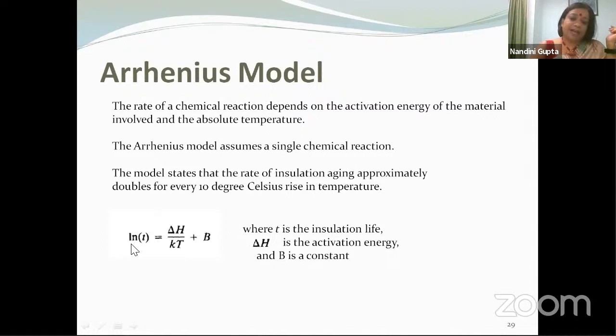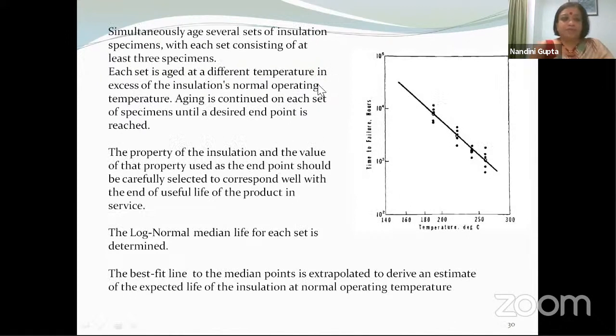It is given by ln T equal to delta H by KT plus B, where T is the insulation life. So you're predicting the logarithm of the insulation life. Delta H is the activation energy and B is a constant depending upon the material. So an example would be how would you set about using this model in your aging test?